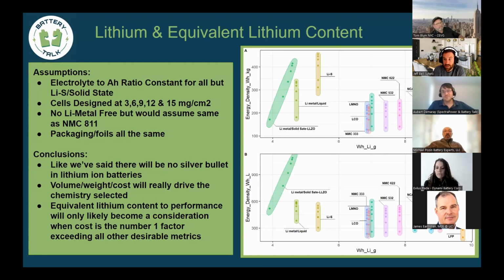That is not necessarily always the case. Right now, this is assuming full conversion, but it is not always the case that you only use one molecule of lithium or half a molecule of lithium per molecule. I'd be more than happy for you to show me the data that proves that out, but last time I checked, that's not the case. Or else all of these numbers at full conversion would be off, right? For example, we know that LFP can get above 200 watt hours per kg. CATL has shown it. If your argument is correct, that does not exist. Well, I think that's at the cell pack level, and with the cell to pack, and a few other changes to the structure, and then the N/P ratio.